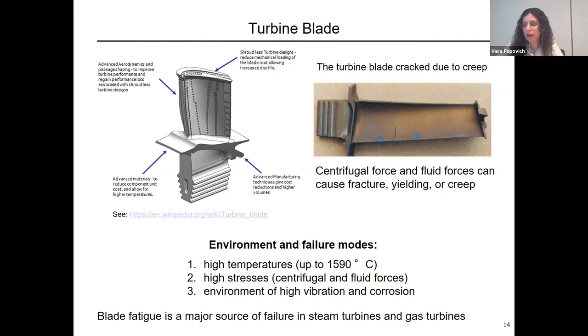An example on the slide, you can see the types of failure and environmental and failure modes that the turbine blades can experience. Really high temperatures, which depend on the engine, but they can reach up to 1500-1600 degrees C, high stresses, centrifugal fluid forces, and an environment of high vibration and corrosion. Quite often we see sulfide degradation, corrosion, and oxidation take place. And on your top right image, you see a turbine blade that is cracked due to creep.